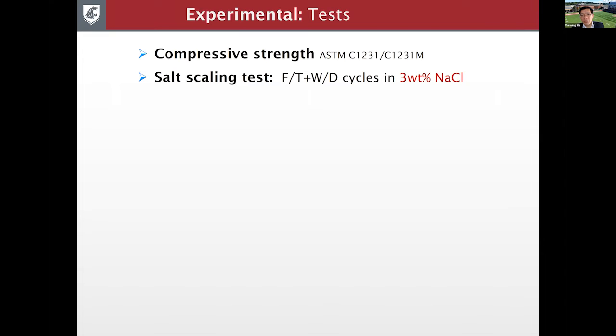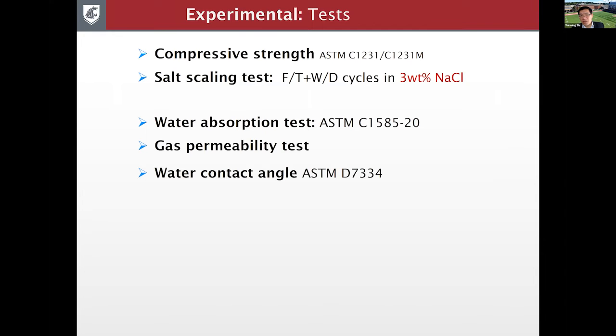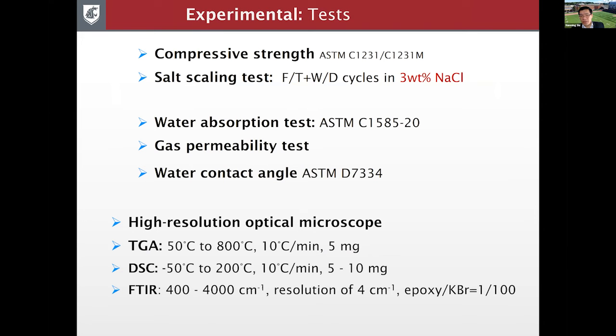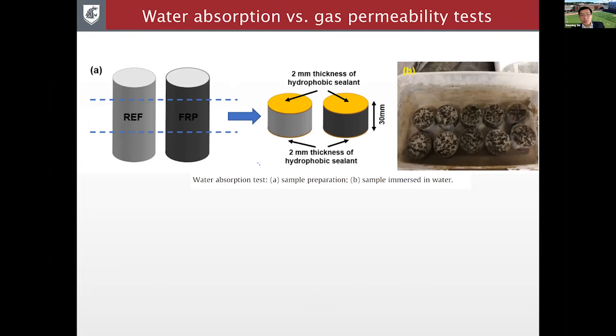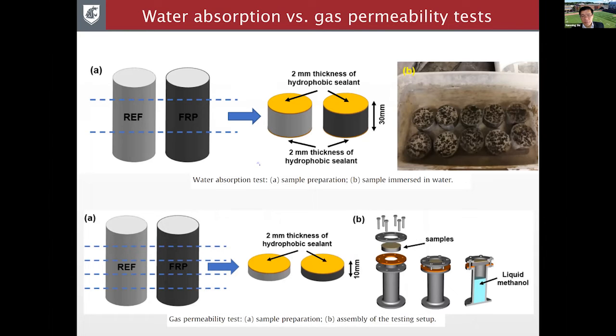So again, a number of tests were run. Some were compressive strength, salt scaling tests, and the more mechanistic ones include water absorption, gas permeability, and water contact angle. And then to shed more light on the issue, we also used optical microscope, thermogravimetric analysis, differential scanning calorimetry, and Fourier transformation infrared spectroscopy. So for the water absorption test, the cylinders were basically cut in the middle to get discs, and then only the sides were not sealed, so that we want to see how water penetrates through that interface between the FRP and the concrete. And for gas permeability, the same deal. We're mostly looking at that interface.